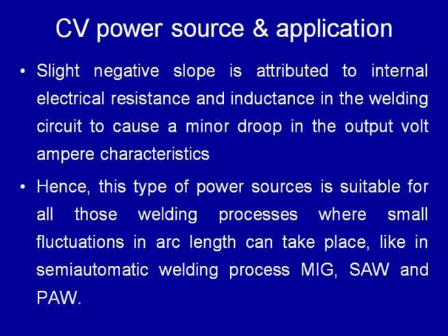So, although these are constant voltage power sources, there is a minor decrease in the arc voltage with the increase of the welding current, and this minor decrease is attributed to the internal electrical resistance and inductance in the welding circuit, which causes a minor drop in the output volt ampere characteristic. So, this slight negative slope is attributed to the electrical resistance and the inductance related aspects of the welding circuit.